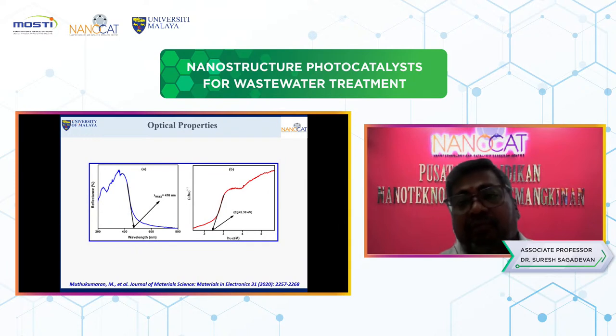As well as, it is very important for the band gap value, how the electron jumps from the valence band to the conduction band for the decomposition process, based on the band gap value. That band gap value is calculated using the Tauc plot to be 2.38 electron volt.